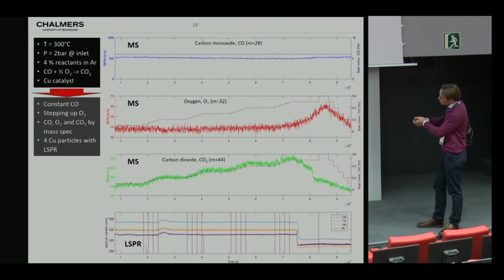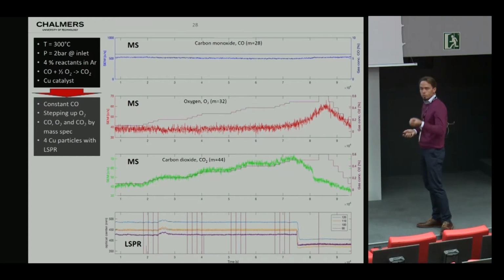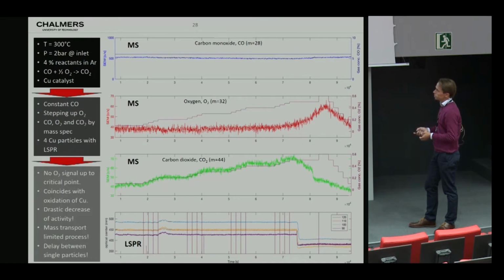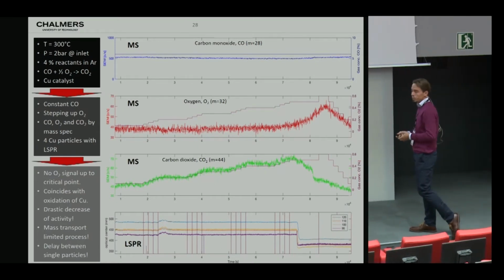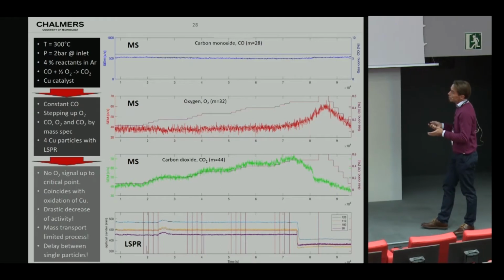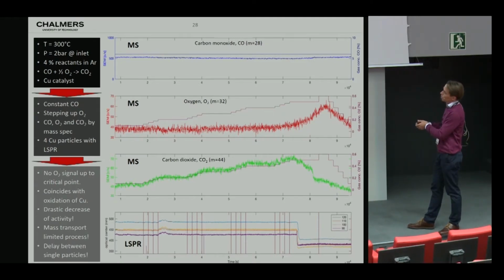And if we now look at the optical signature of the 4 particles in the channel, this happens when they undergo the transition from the metallic state to the oxidized state. What does this tell us? Well, it tells us that, as we've known beforehand for this particular system, the metallic copper is the much better catalyst for CO oxidation than copper oxide. But it also tells us that we are able to operate this reactor in a completely mass-transport limited regime.